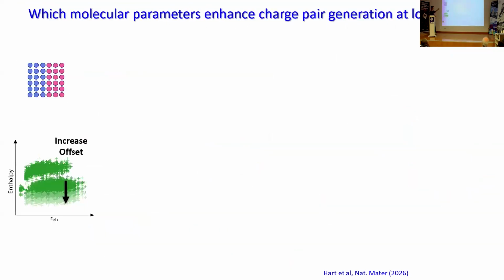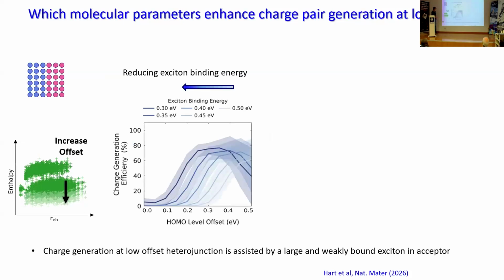When we apply it to the question of photocurrent at a heterojunction, we look at the efficiency of charge pair generation as a function of this driving force, this offset. What we're interested in is what if we change some parameters associated with the molecules, how would they affect this? The thing that we saw when we compared ITIC with Y6 was this trend that the photocurrent turns on as the driving force goes up, but it turns on earlier with Y6 than with ITIC. And what could be the reasons for that?